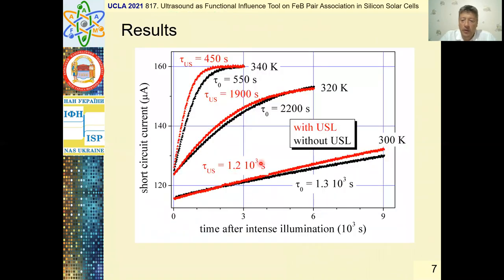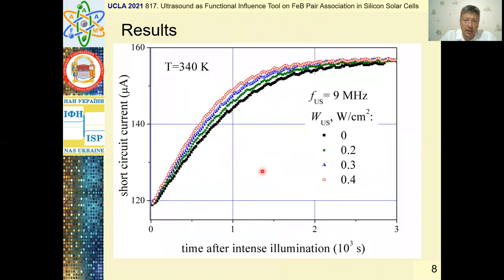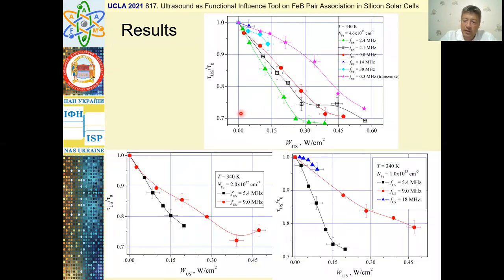It was revealed that ultrasound loading leads to accelerating of Iron-Boron Pair Association. The effect value depends on ultrasound intensity. The next slide demonstrates that decrease in association time is linear, depends on intensity in initial stage, and then effect saturation is observed.